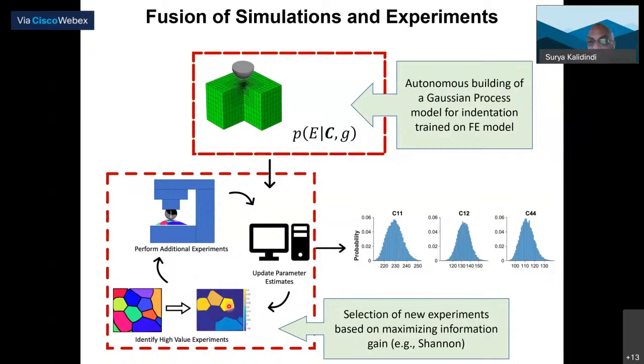So the system does an indentation there, takes a value, and goes back to asking, okay, what did I really learn from that measurement? Did my estimates of the elastic constants really change? And if they didn't change, then where should I do the next indentation so that my ability to understand physics gets better? This is the loop that we have done in a less than fully autonomous system. And it's amazing because, for example, for elastic constants in cubic crystals, if you do 4 indentations in properly selected grains, you get pretty much the answer. After that, you're not getting much further improvement in the estimates of the single crystal elastic constants from polycrystalline samples.